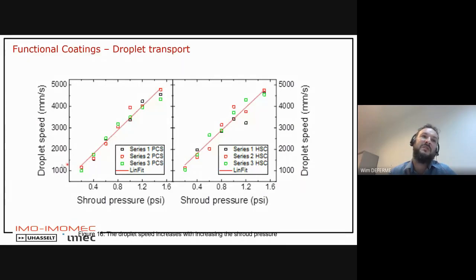So we measured the speed of the droplets in comparison to the shroud pressure, and of course you see the higher the shroud pressure, the higher your droplet speeds, going to a few thousands of millimeters per second for these droplets. And this is a perfect relationship that could be measured for the shroud pressure. This is a correlation from the PCS, photocorrelation spectroscopy. And these are the high-speed camera images, and you see more or less the same. So we compare both techniques, and we see that both techniques are giving the same results.